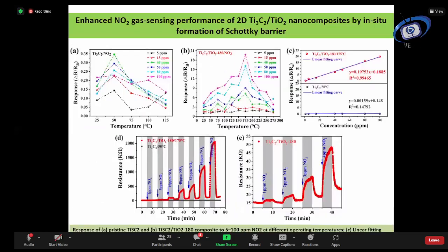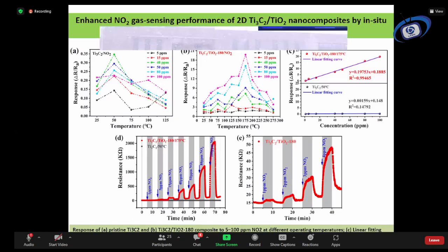And these are typical curves, just supporting data, for different concentrations that have been tested at different temperatures and different parameters, and a linear response has been seen. Also, it shows a maximum linear response of 0.9, and that is more than ideal. Because it is very important to find the detection limit as well. So in this case, our detection limit was about 3 ppb for nitrogen dioxide gas. And next is for SnO2.